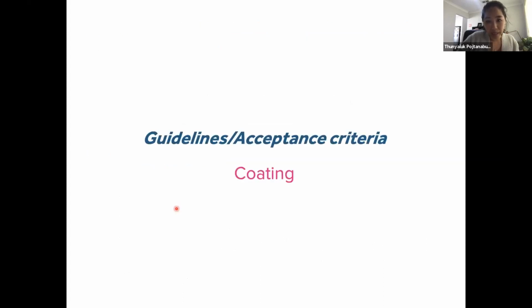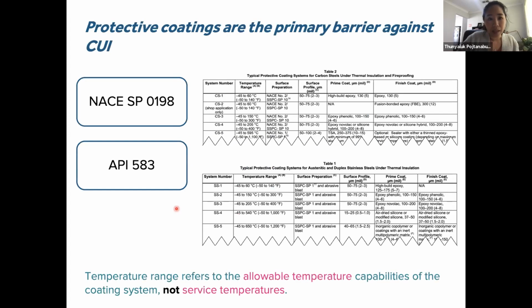So on the coating side, which is a key barrier for CUI, at the moment in the industry, there are two standards. One is NACE and one is API, and they both refer to these two tables, showing the selection of coatings for different operating temperatures. So for example, if the temperature is somewhere around 100, there are a few coating classes that could potentially be used.